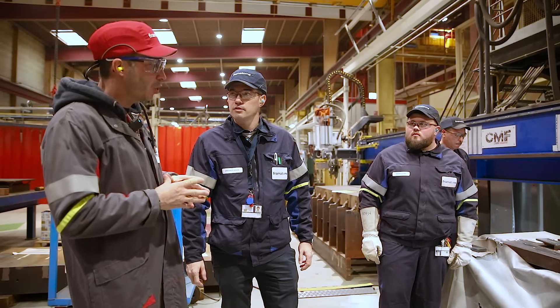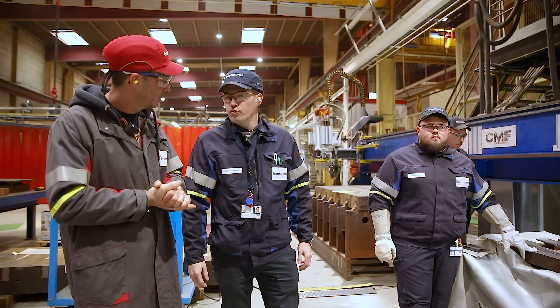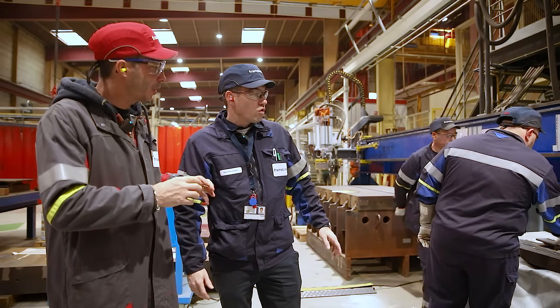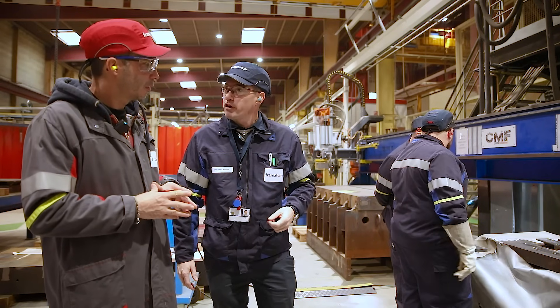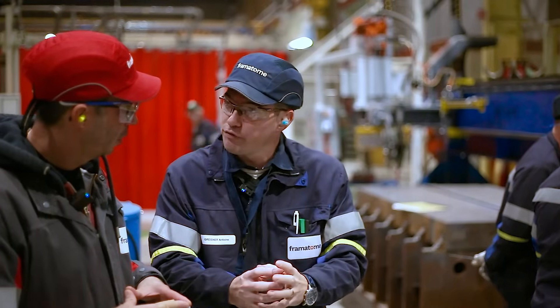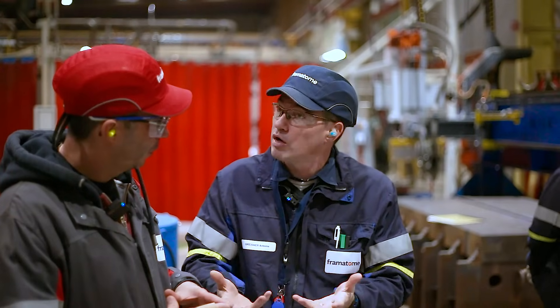Antoine explains submerged arc welding (soudage fil-flux): it is the equivalent of shielded metal arc welding but for heavy-duty work, welding thick sections with high metal deposition. Instead of a metallic core like a coated electrode, there is a solid wire of diameter 4 mm. Instead of a coating bonded to the wire, a pre-dried flux powder is fed down around the wire, which protects the weld pool and deposits a weld bead just like a coated electrode.